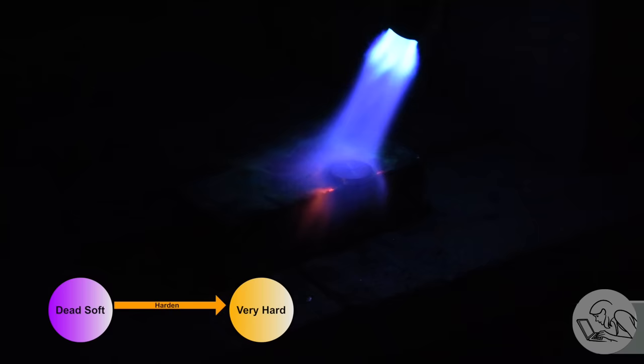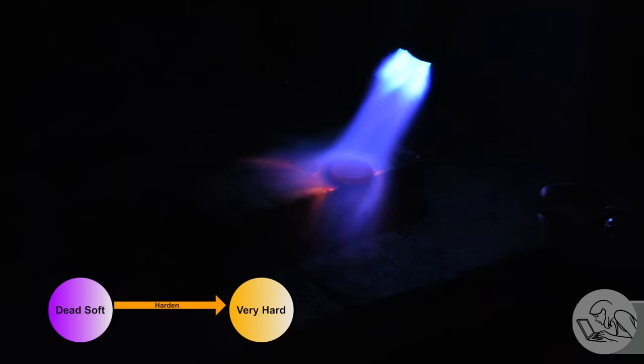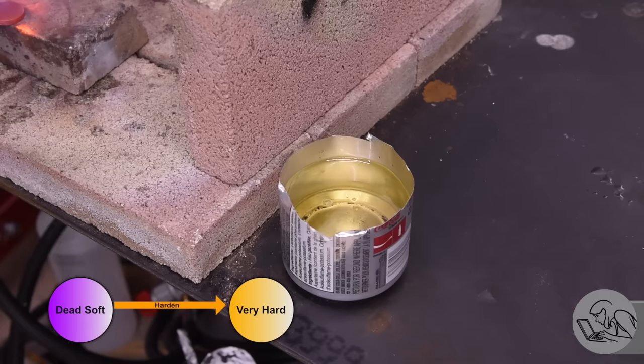It is possible to overheat it doing this with certain types of tool steel, so don't go bananas, but just make sure to hold it at that orange temperature for a while to make sure that the heat has soaked all the way through. And then it's time to quench.